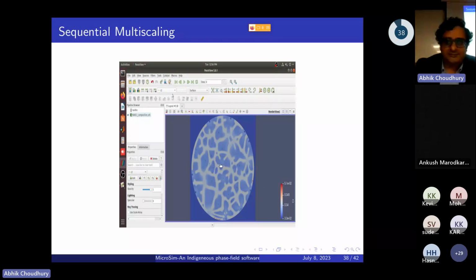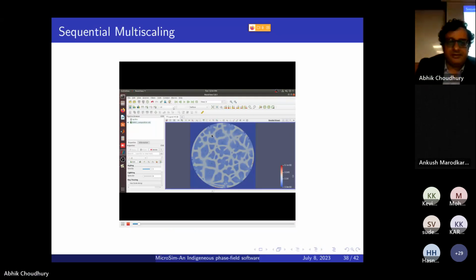This is one of the features I like the best, and it is relevant for any through process modeling that you would like to do. I will give a brief demonstration of how this works, and I have named it sequential multiscaling, in the context that you do a solidification simulation and you extract a part of the microstructure for post-processing. That means you would like to know how that particular microstructure would evolve during subsequent processing, for example, heat treatment. So what you would need to do is take a relevant part of the microstructure out from a solidification microstructure and do the corresponding lower length scale simulation, and therefore I have referred to it as sequential multiscaling.